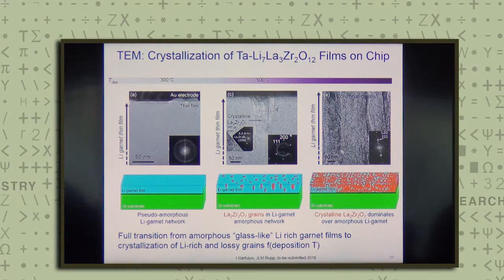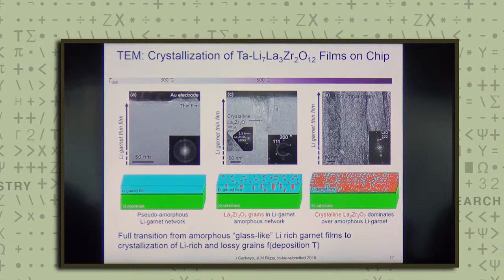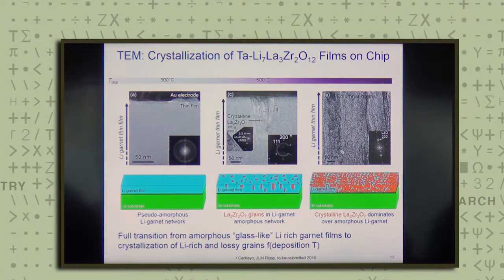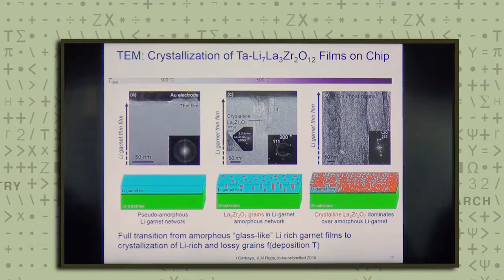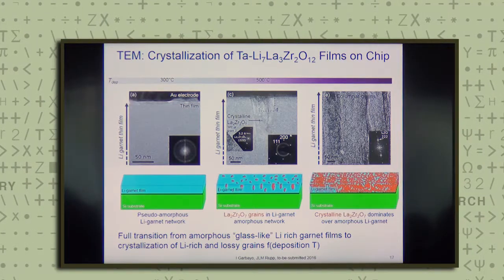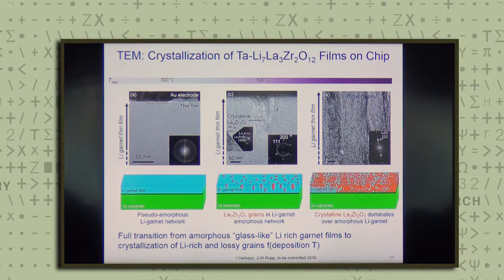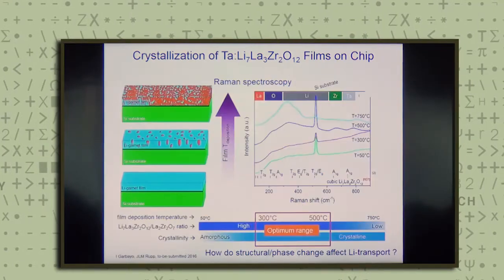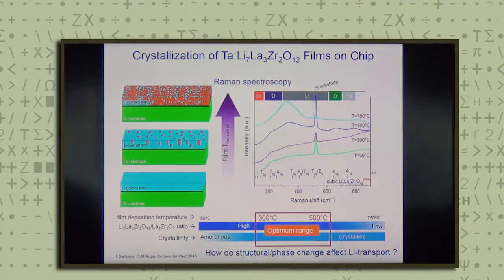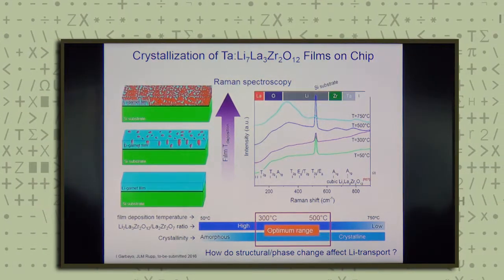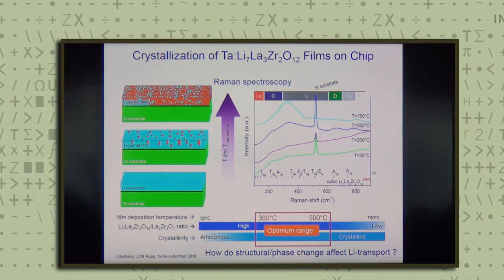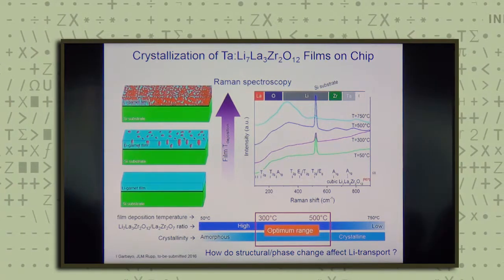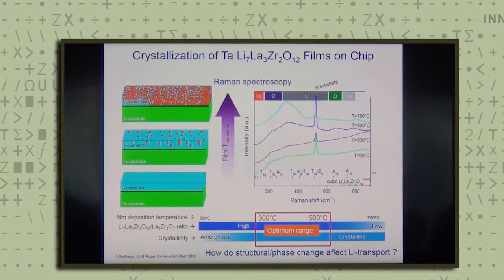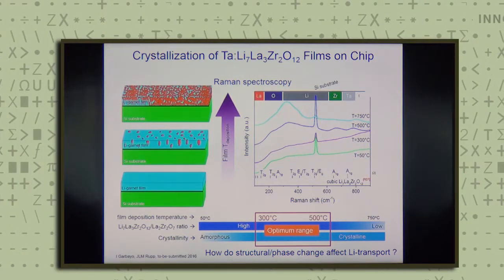So this is currently unpublished. And what a lot of people don't know is that you can create the whole arena from these amorphous structures to the fully crystalline structures that you would normally find in classic batteries. What is interesting here is that we found, describing the lattice a bit further, that it's always kind of like a lithium garnet near order, even if you're amorphous and you just start to crystallize. And when you arrange a periodic long-range order, you come to the classic crystalline structure like in a large-scale battery.